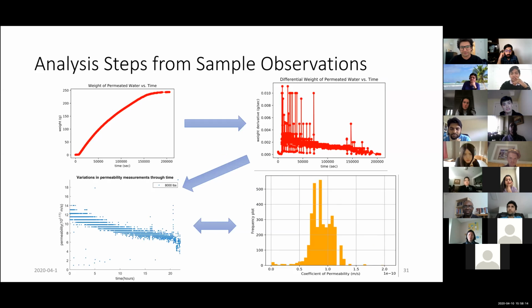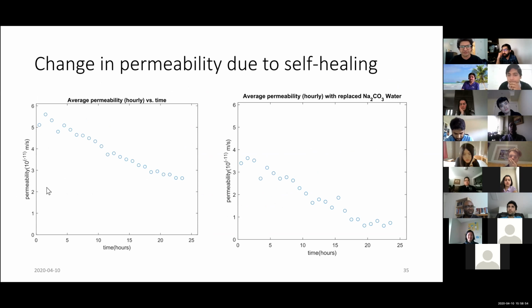Basically, after 1 or 2 hours is when the experiment stabilizes, and after that we take the reading. So I just assume that during that time enough water has passed through the concrete system so as to now be a sodium carbonate saturated system. But you are right that inside the sample itself there is also some water stored. So to differentiate whether the effect is coming from sodium carbonate addition or the water that was already present and helps in the hydration, to quantify that is tricky.